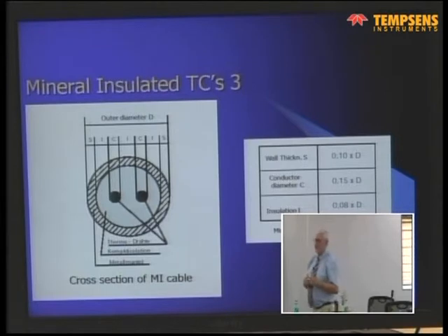The welder himself does not like the material because it forms a thick tip, and so he has a problem with the insulation resistance. So not everything is ideal, and so we had about 4, 5 different vendors for the mineral cable, even for type K, with different characteristics, and we selected the material according to the application, if we had a good knowledge of the application, of course.